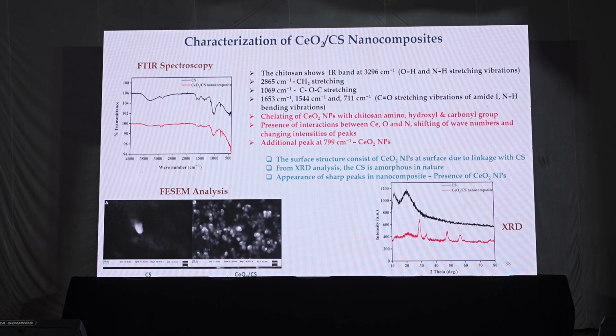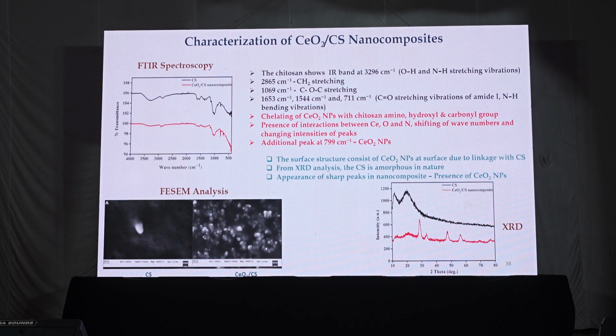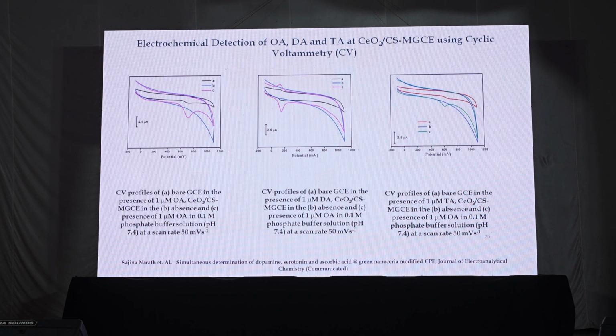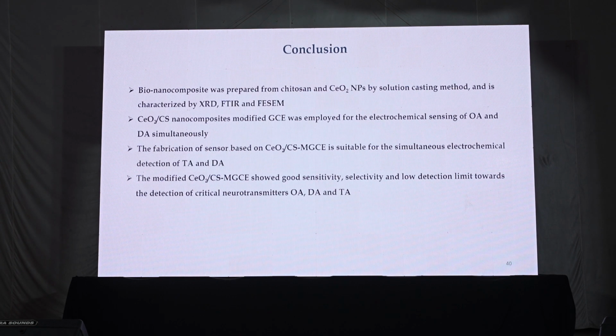These are characterized using FTIR spectroscopy, XRD and SEM analysis. The CV profiles were studied with the modified glassy carbon electrode in the presence of octopamine and tyramine. And we have effectively determined the presence of dopamine at ppb levels. The bionanocomposite was prepared from chitosan and cerium dioxide nanoparticle solution using the solution casting method, and it is characterized by XRD, FTIR and SEM.